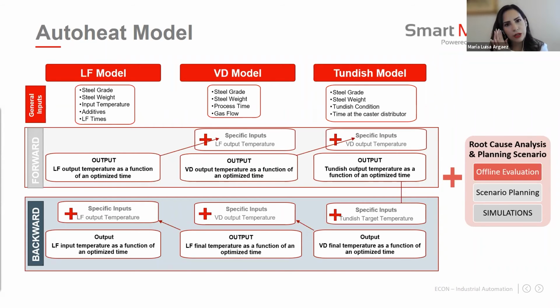With the tundish objective temperature and the CCM speed, with the backward modality, we can obtain the final temperature in the VD and in the LF, and the initial temperature in the ladle furnace. Here, it is important to say that the estimation of each model is an input feature to the consecutive model. Each stage has different features like weight, grade, transfer times, additives, among other factors, and descriptions of operational signals.